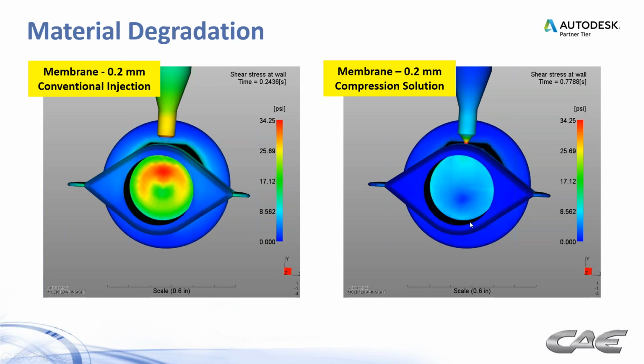It's not just this type of part. You see it in automotive parts as well. You know, the thinner and thinner you get, and especially with more amorphous type materials, the higher that molded in stress goes. And the higher that molded in stress goes, if that part has to hold some sort of a load, you may end up with quicker failure, not just because it's thinner, but also because there's a larger amount of molded in stress there.